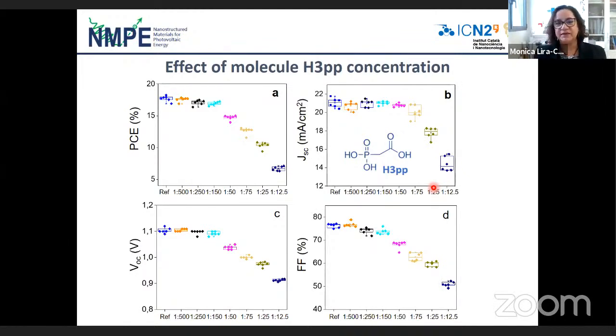You can see here below that the blue one is the reference, and our best one is this one. You can see that we were unable to improve the efficiency. Here's the voltage, also very similar. We have never been able to increase voltage above the reference without the additive.